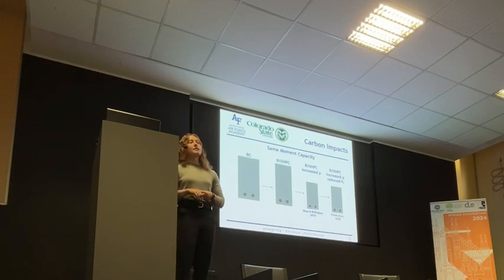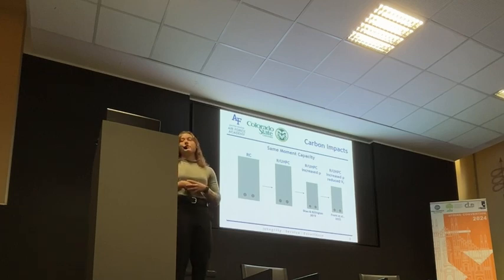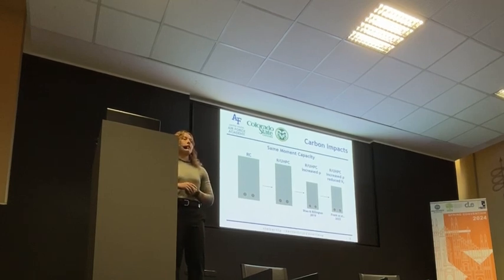And so some of the carbon impacts, this is a very fundamental arbitrary progression of how we made our UHPC more efficient. As you can see on your left, this is just a normal cross section of ordinary concrete. And if you were to assume that UHPC has 2.5% more cement within the mix, but that its lifespan is 2 times longer than normal concrete, you can progress and make it more efficient. From the first specimen to the next, we assumed the same reinforcement ratio, but instead of normal concrete, it's UHPC, and you can reduce the volume by 10%. Not a huge impact on the amount of cement you're using in your specimen,